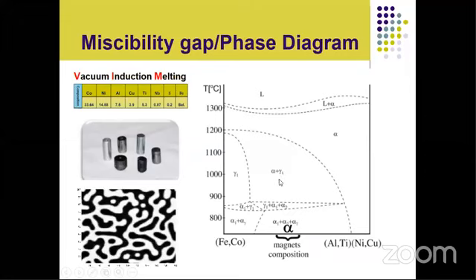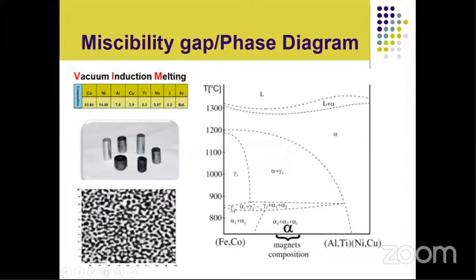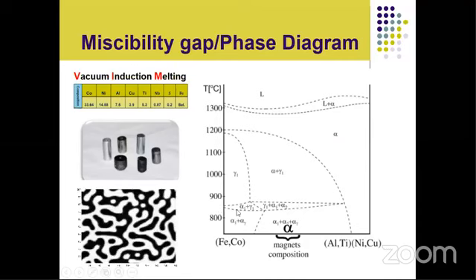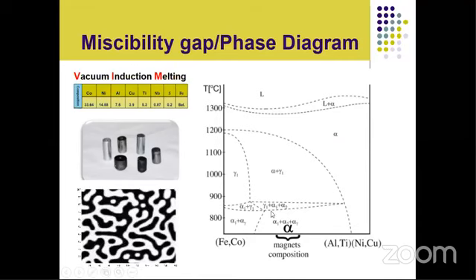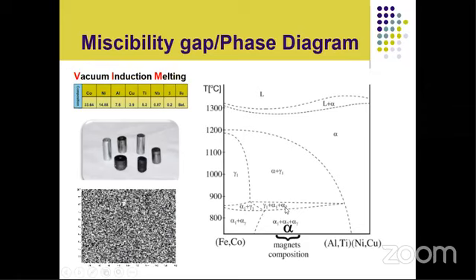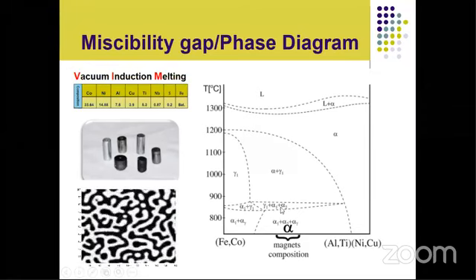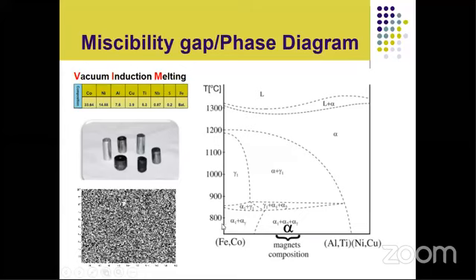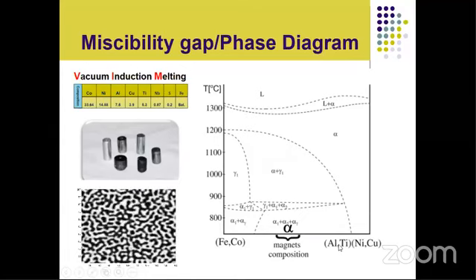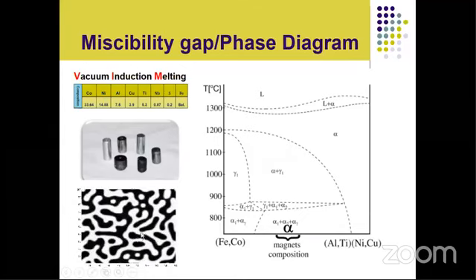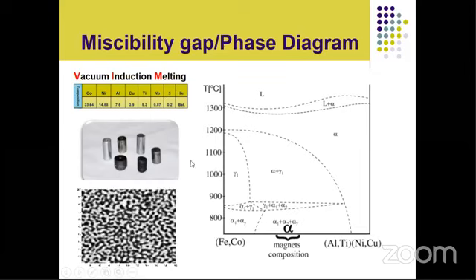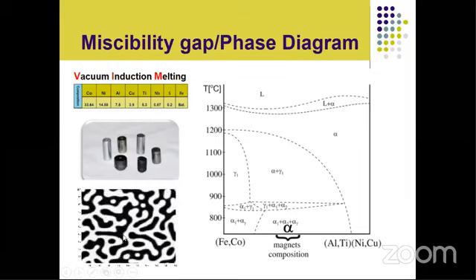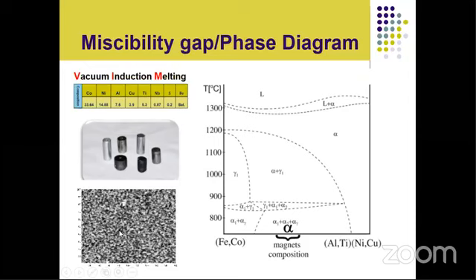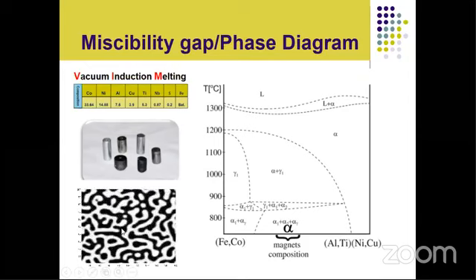But when we quench this material across this temperature, which is close to the Curie temperature of the alloy, it splits into two phases, alpha 1 phase and alpha 2 phase. This splitting is actually due to the miscibility gap between alpha 1 and alpha 2. Here you can see the animation that when we quench the alpha 1 phase, it will split into dark and white patches. These are actually alpha 1 and alpha 2 phases.